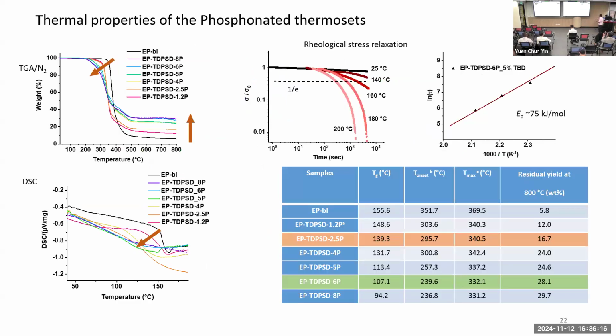And you can see by having different amounts of phosphorus in the resin, you can influence the thermal property of the material. You tend to have very high char when you have higher phosphorus. You can see this violet curve. This has the highest char because it also has the highest phosphorus in the structure. However, when you have higher phosphorus, you also have lower thermal transition temperature, which is glass transition temperature, TG, of the material. So you need to be aware of it. And what is very important in case of vitrimeric or in case of covalent adaptable network is the transition temperature.